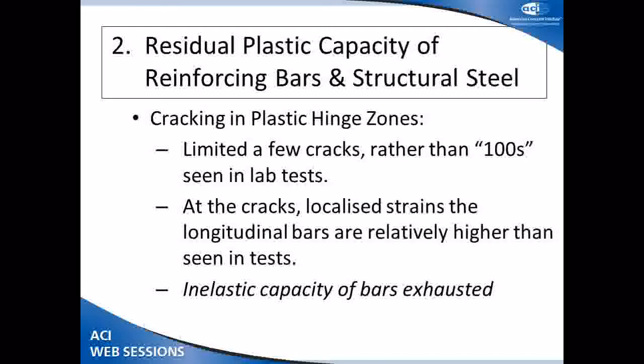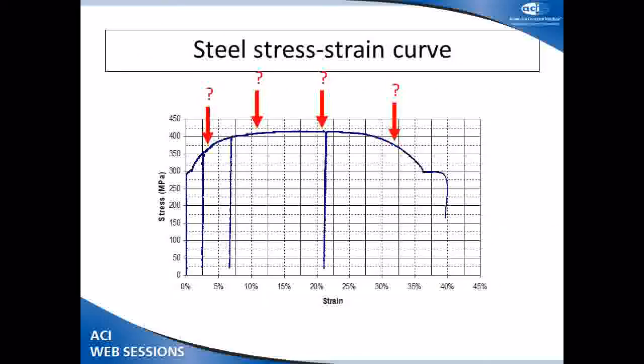to distribute the plasticity. When we actually went in and measured the plasticity, we were finding that bond loss or yield penetration was about 1 to 1.5 bar diameters, not the 3 to 4 that's in the textbooks either side of the crack. So the local strain in the bars was 4 to 8 times higher than we expected. Fundamentally, the question is, if this is an actual stress strain plot from a bar we took out of a building, where are we on that curve for that bar?